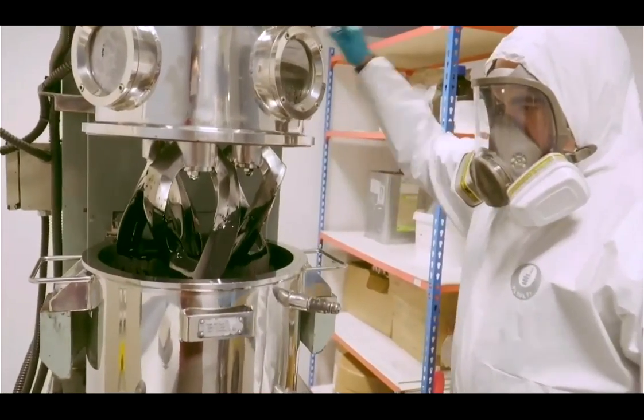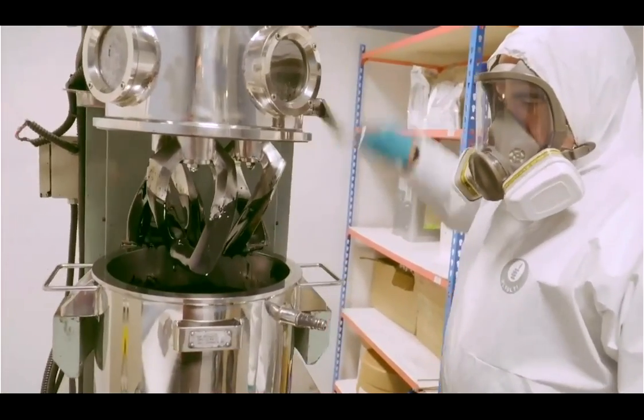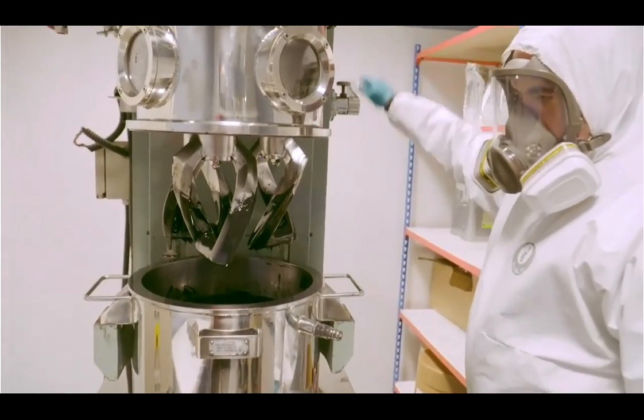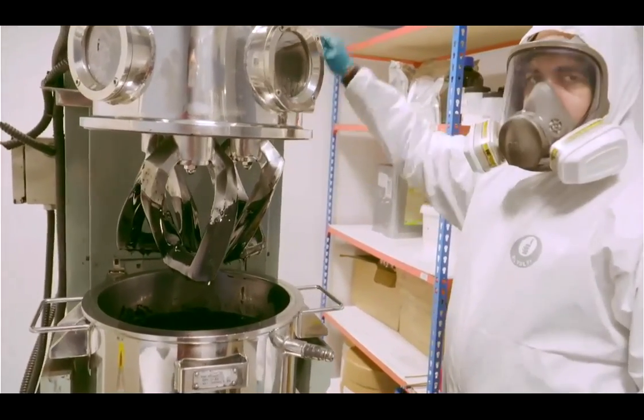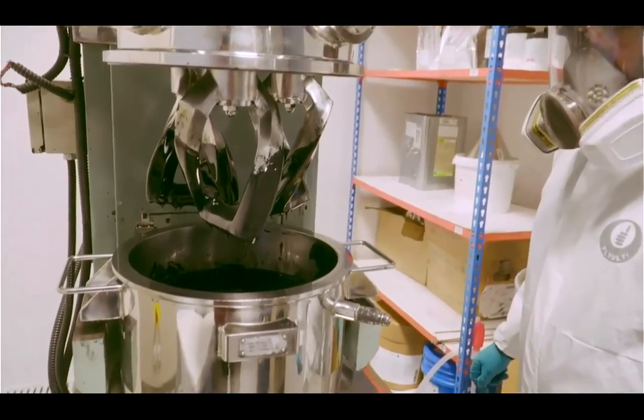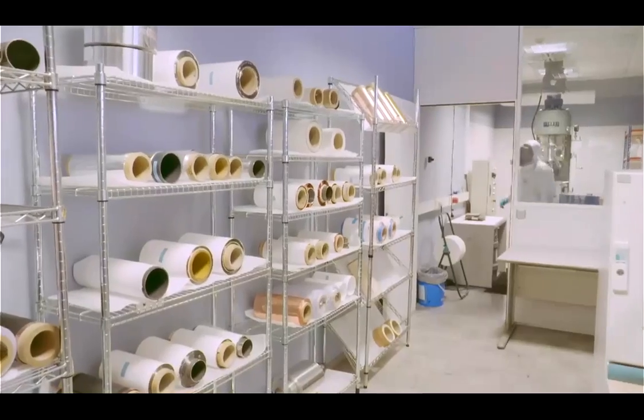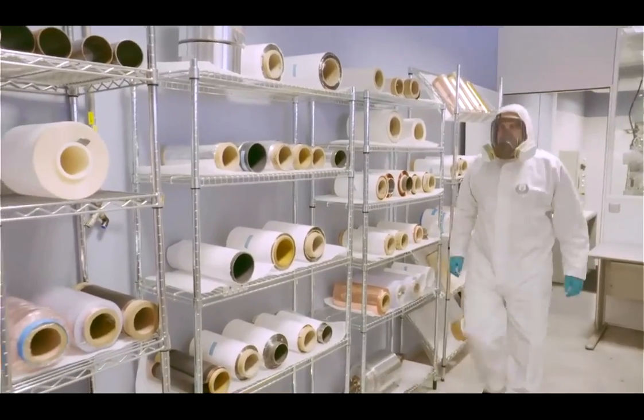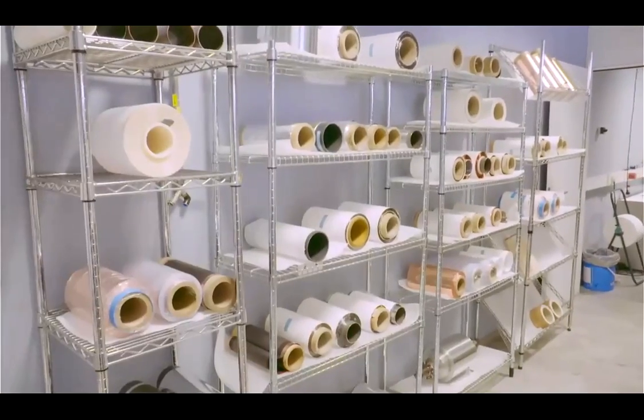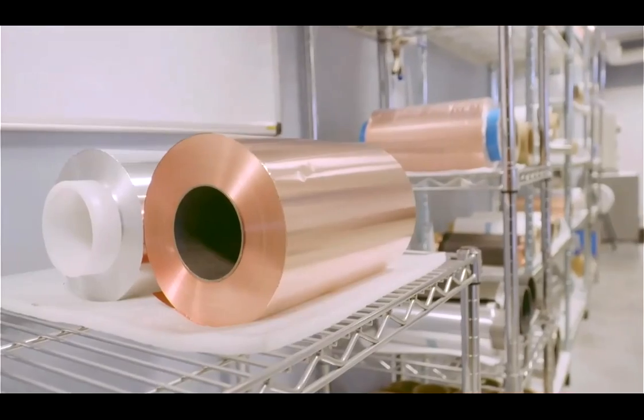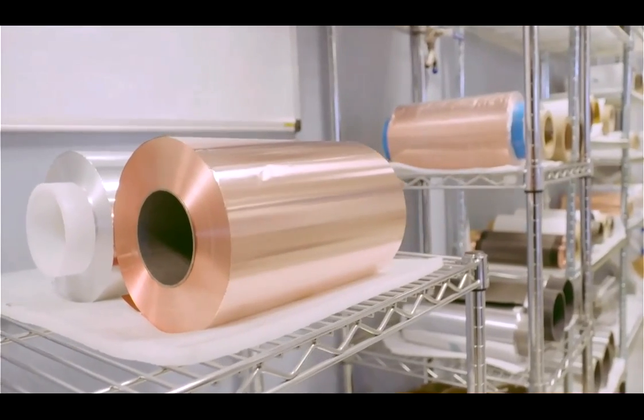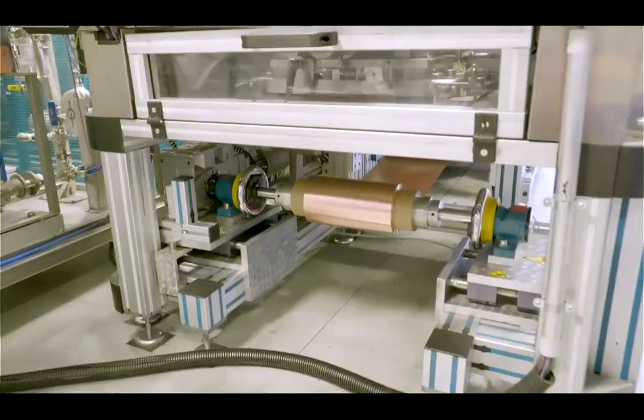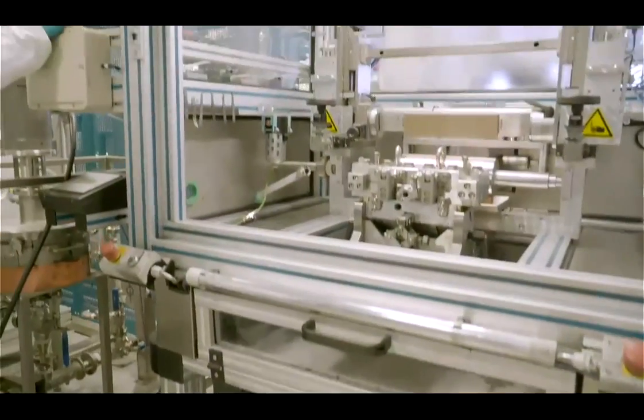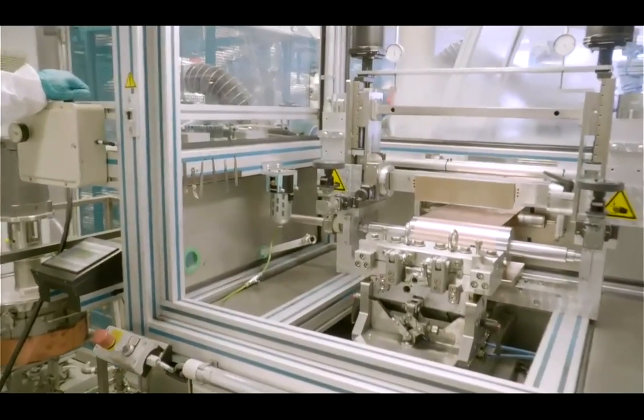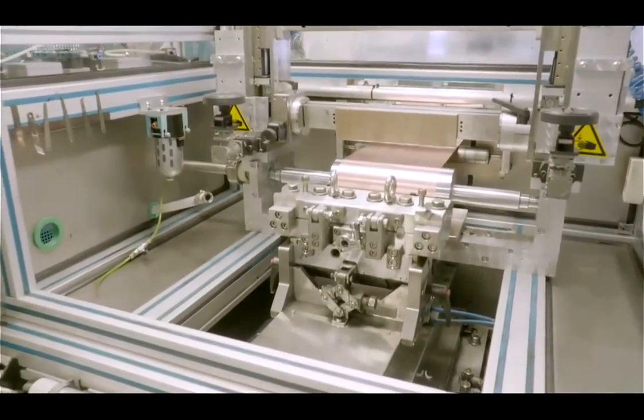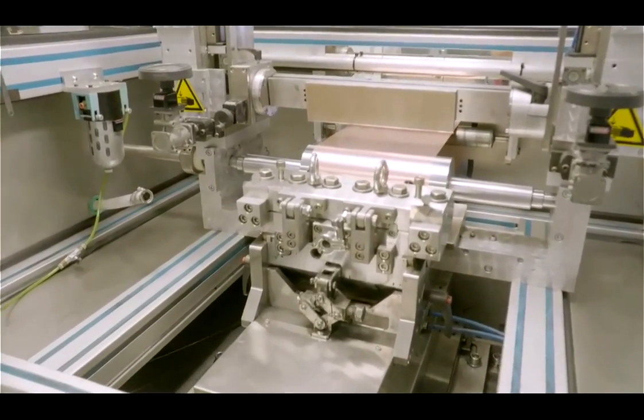Okay, the typical formulation for the cathode is composed of the active material, which can be LFP, NMC 111, 532, 811, approximately 95% in weight, conductive material, carbon, 5%, and binder PVDF. In general, we process these materials in water, but it is much more difficult to process them in water than the graphite.